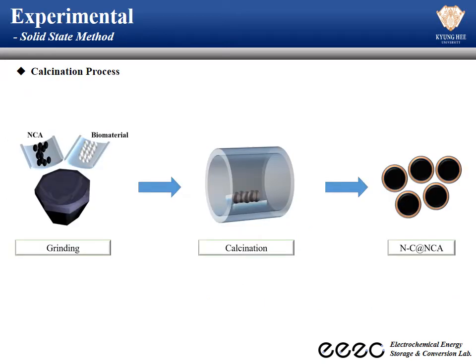To form the nitrogen-doped carbon coating layer, the solid-state method was used. First, NCA is ground so that it can be evenly mixed with the biomaterial, which is a coating source of nitrogen-doped carbon, and then calcination is performed at 500 degrees to obtain the nitrogen-doped carbon coating layer on the NCA. From now on, the NCA on which the nitrogen-doped carbon coating layer is formed will be called N-C@NCA.